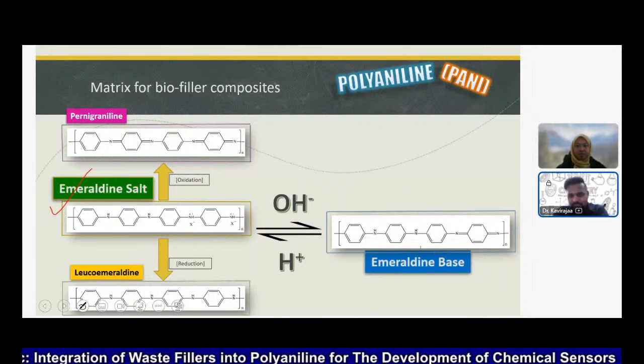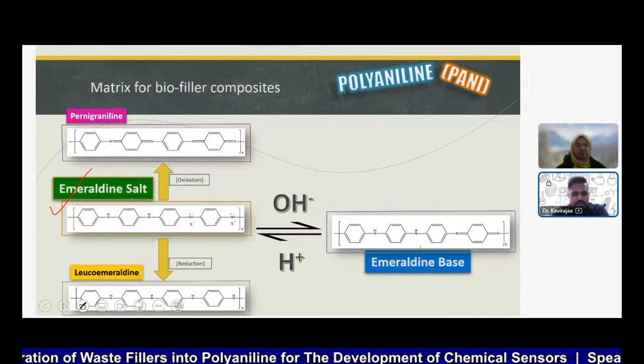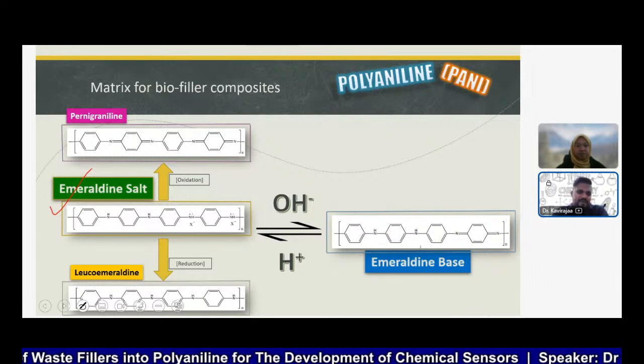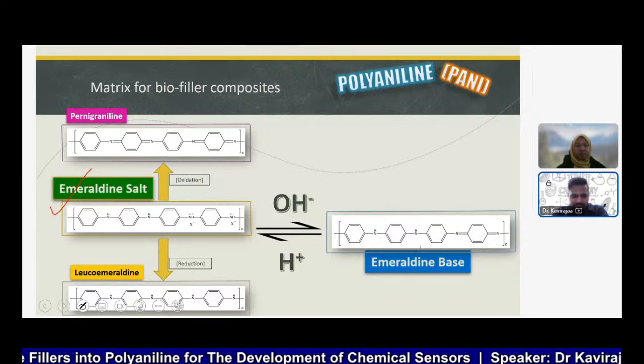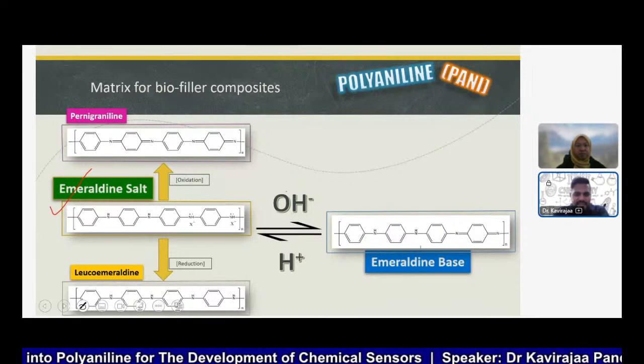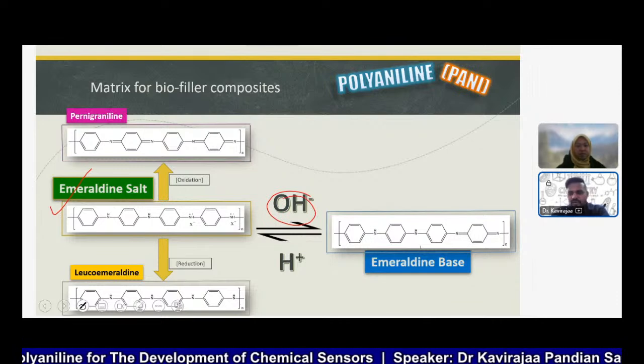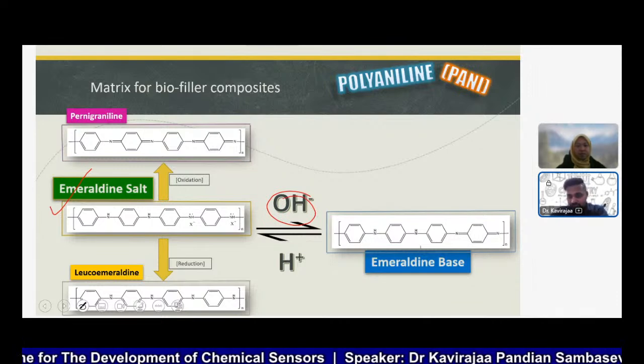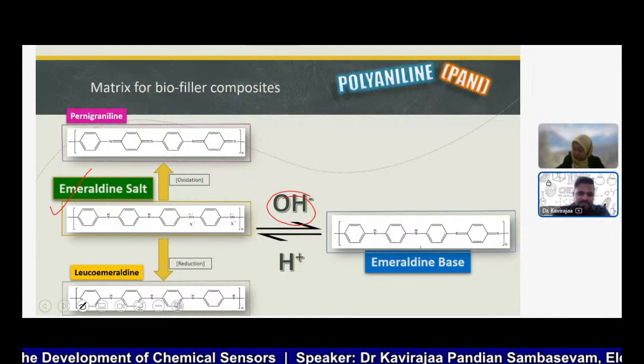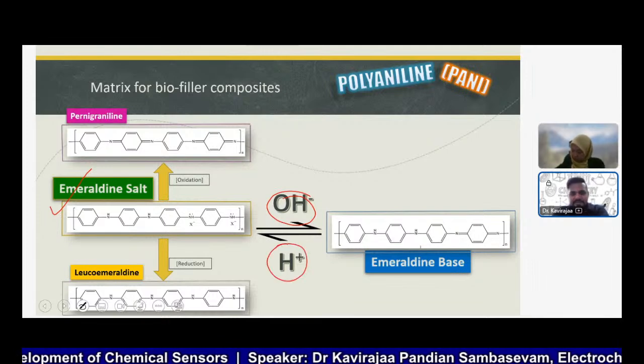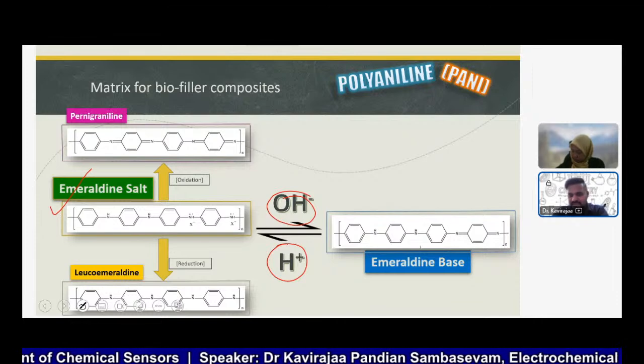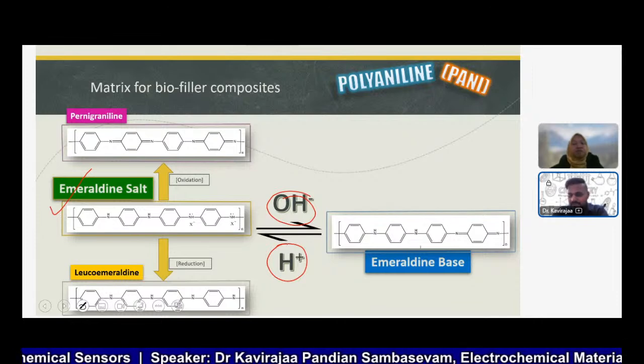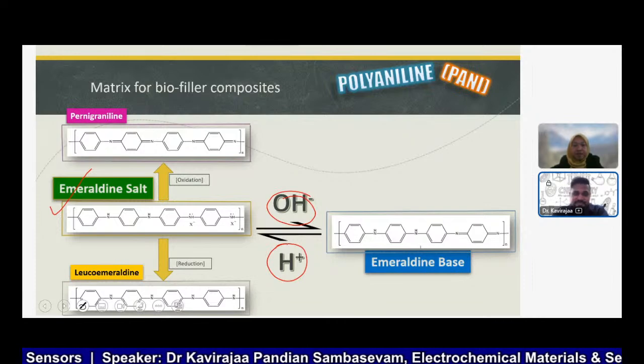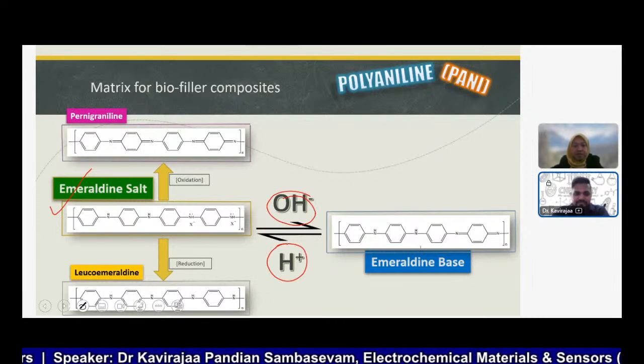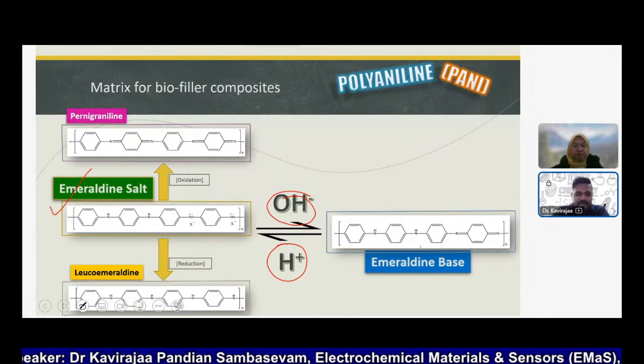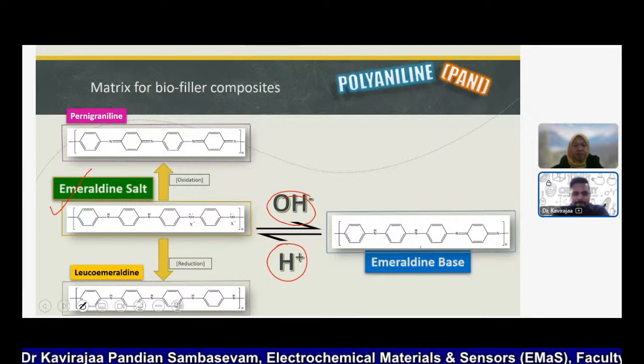That's why I put in the color labels as well over here. So, very simple chemistry about this emeraldine salt, or this conducting polyaniline, is that when we let it react with any type of base, it will be converted into emeraldine base, which will look blue in color. And then immediately we can revert it back to the green color emeraldine salt by letting it react with an acid. Normally we use hydrochloric acid, or we can also use weak acids. But definitely weak acids will take some time to reprotonate, I mean to redope, this emeraldine salt.